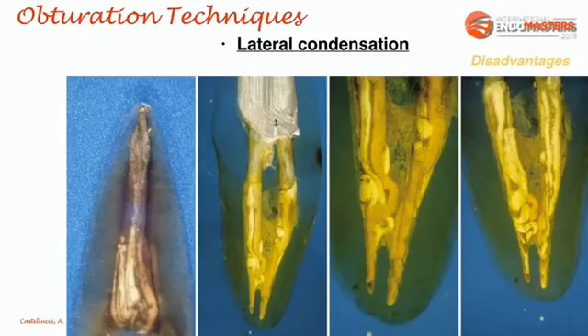Only with difficulty can one condense several auxiliary cones next to the master cone in the most apical portion of the root canal. As a consequence, one frequently obtains an obturation performed with lateral condensation technique in the coronal 2/3 of the canal and an obturation presented by a single cone surrounded by a bit of sealer in the apical third. Especially considering that heat is not used, the most apical portion of the master cone does not undergo any modification if it does not descend deeply with the spreader. The seal is therefore completely entrusted to the sealer, while the gutta-percha cone will serve the same function that a silver cone or a single cone of gutta-percha will have.